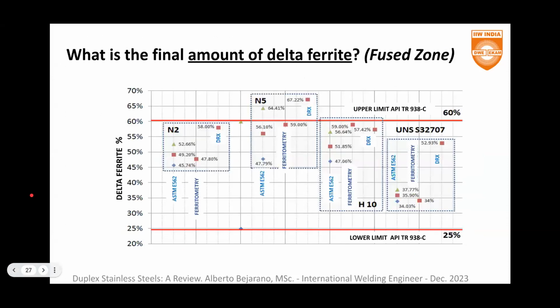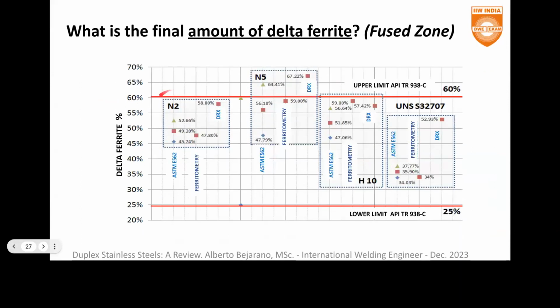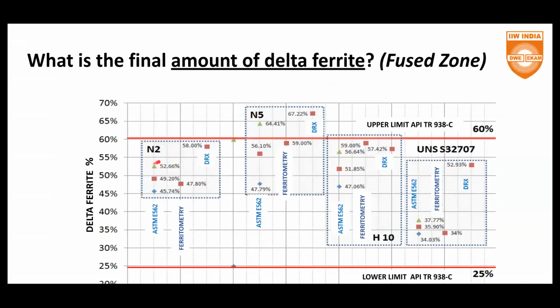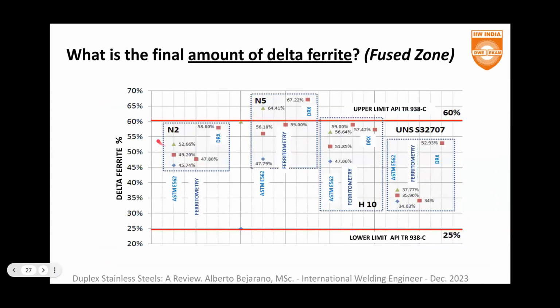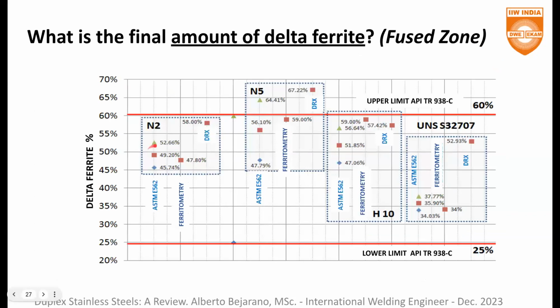36%, okay? This is the value of my base metal, right? And by the use of 2% of nitrogen, 98% of argon, we obtain this value, 49% of ferrite, okay? Which is not bad, because we are